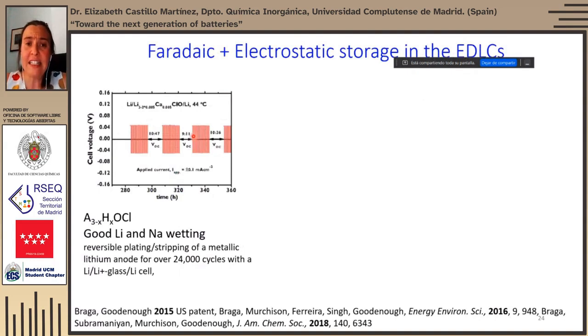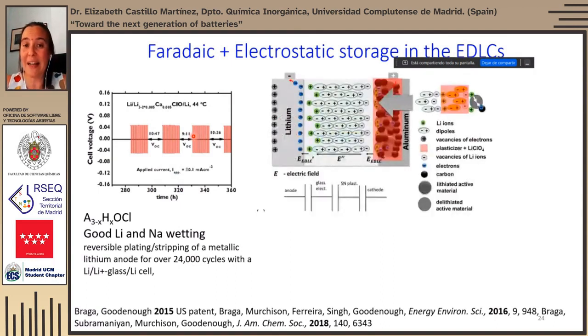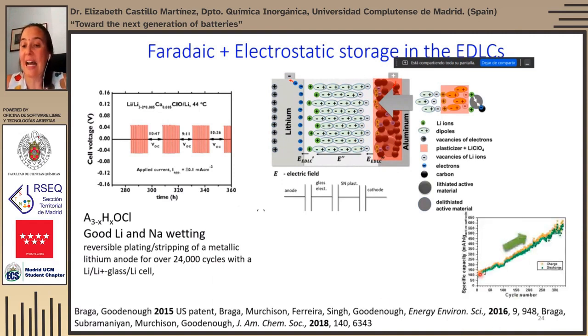And very interesting features are being shown by this glass electrolyte, which seems to be contributing also to the capacity of the materials. So when making batteries with a lithium metal and a cathode material, not only is the capacity from the cathode and lithium achieved, but it seems that there is an additional contribution coming from the electrochemical double layer capacitors that are formed on the surface of the electrode. And this is seen as an increase of the specific capacity with the number of cycles, which is actually very unusual and not really seen in most usual lithium-ion battery materials. I mean, at least in conventional insertion, intercalation, or conversion.